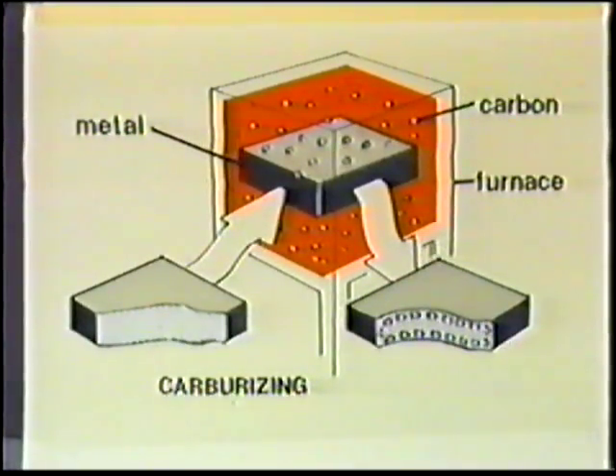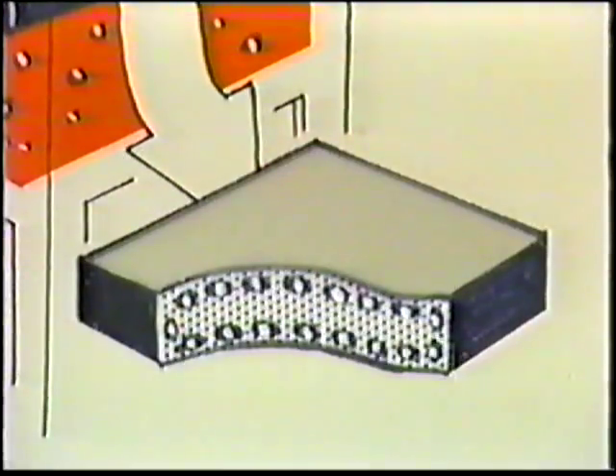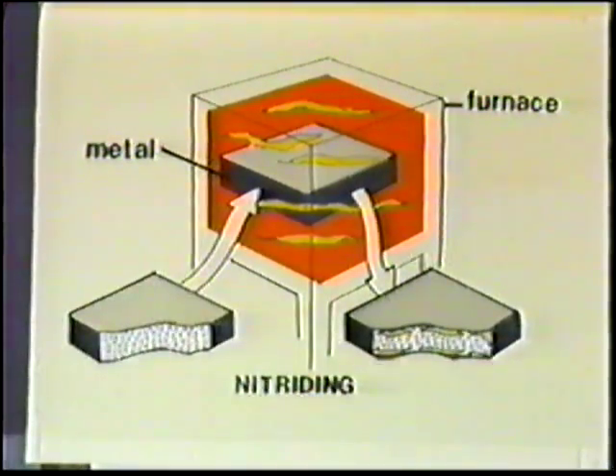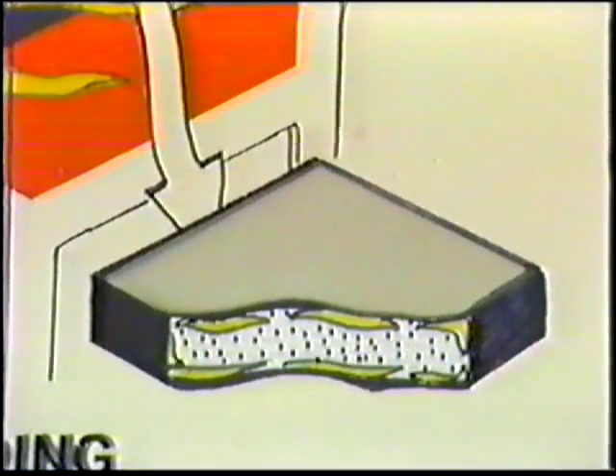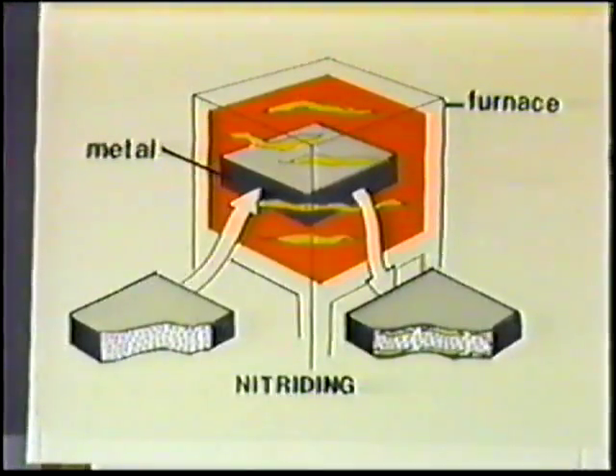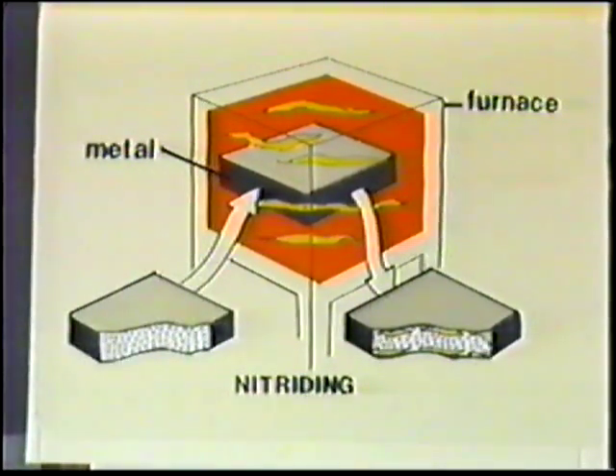In carburizing, low-carbon steel is heated at from 1650 to 1750 degrees in an atmosphere rich in carbon, such as propane. Carbon is absorbed into the surface, creating greater hardness. In nitriding, steel of special composition, usually containing aluminum, is heated in an atmosphere of ammonia. Nitrogen from the ammonia is absorbed into the surface, also creating greater hardness. An advantage of this process is that it requires temperatures of only 900 to 1,000 degrees, which reduces the possibility of part distortion.